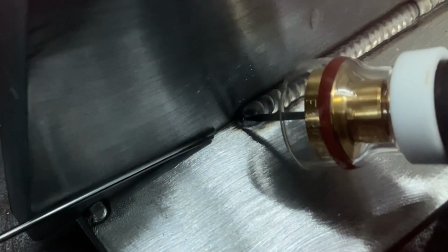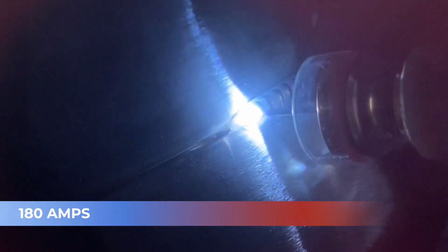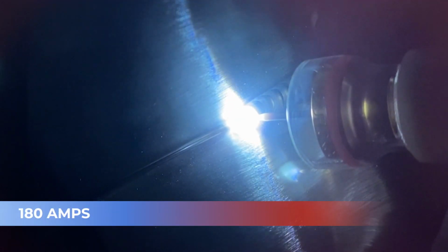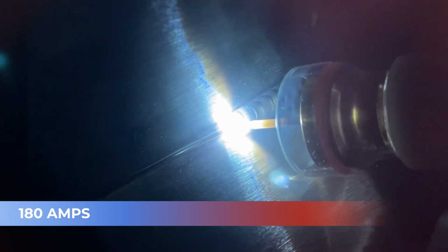I'm able to feed wire and maintain a steady pace and not have to wait. It's free flowing. It's moving the way it should as far as the puddle is concerned. And that lets me know that I'm right in the ballpark of where I need to be. And then from here, we're going to step it up to 180 amps just to show what too hot or borderline too hot of a puddle on a fillet weld and a T-joint like this looks like.